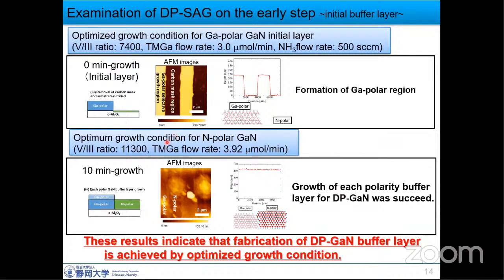Following the AFM image of each polar buffer layer, we confirmed that growth of each polar buffer layer for DP GaN succeeded. From this slide, these results indicate that fabrication of the DP GaN buffer layer was achieved by the optimized growth condition.